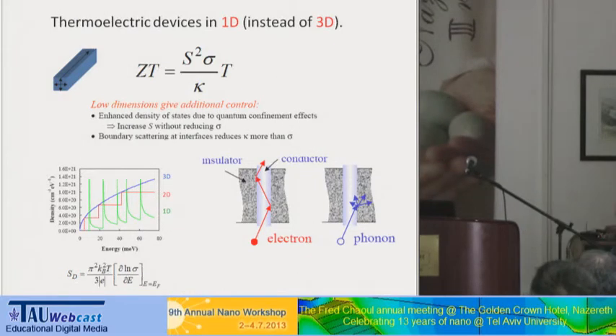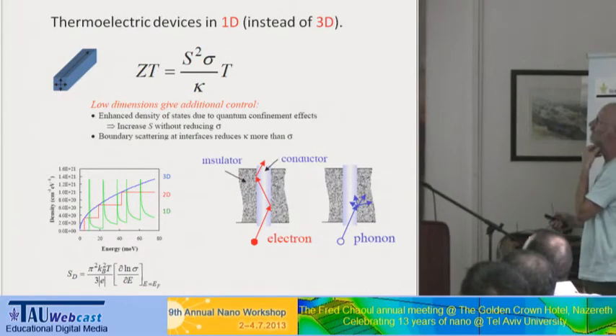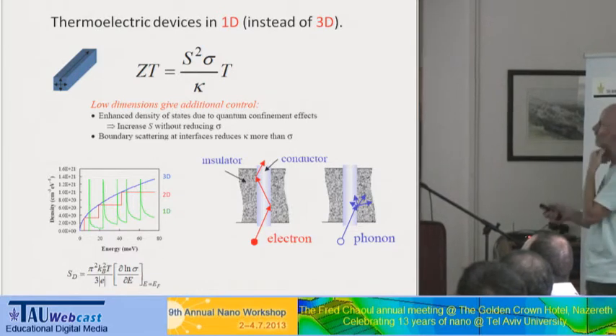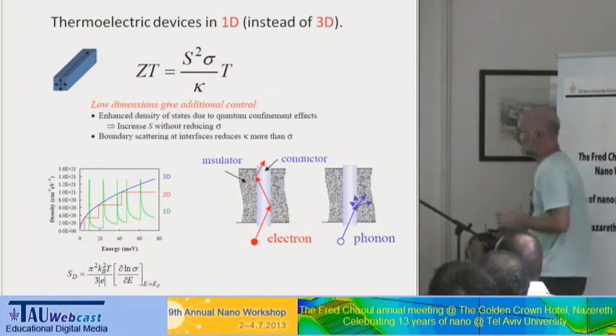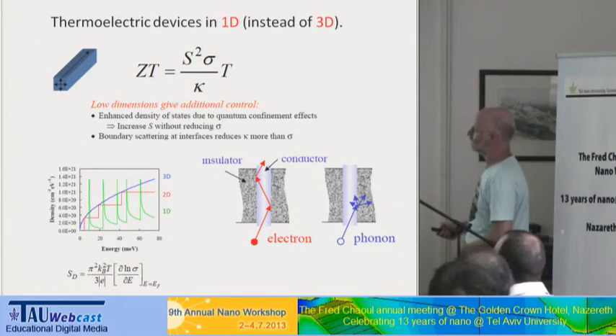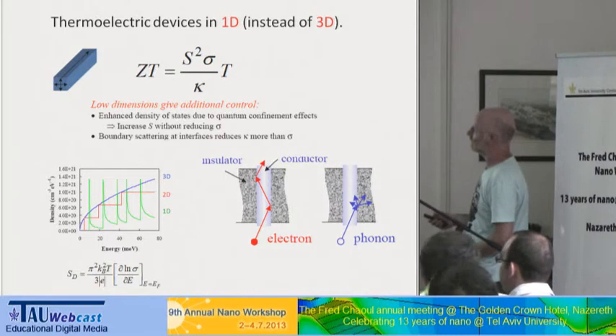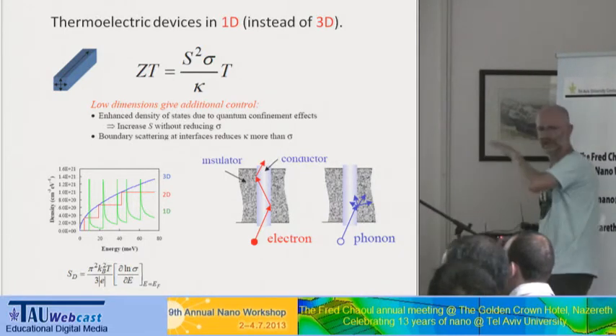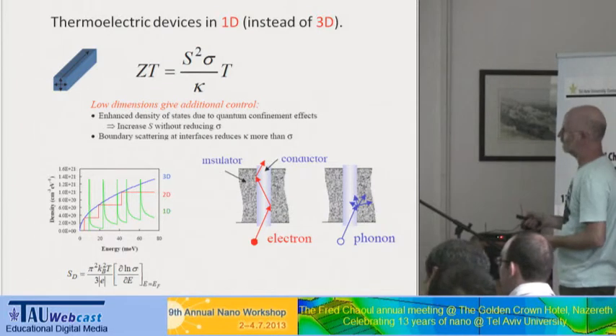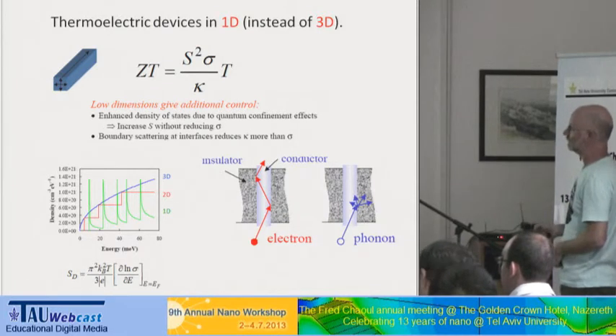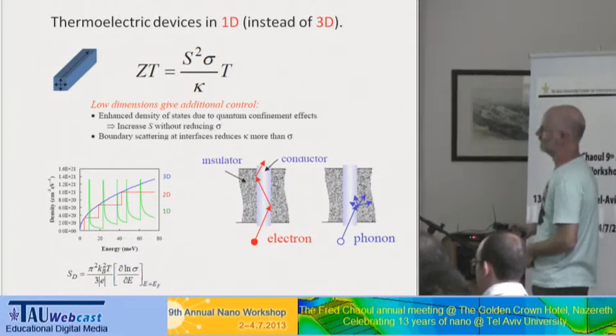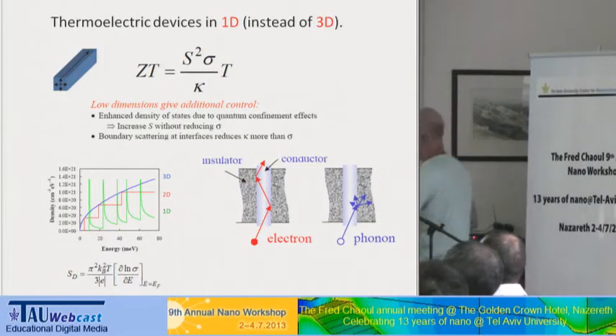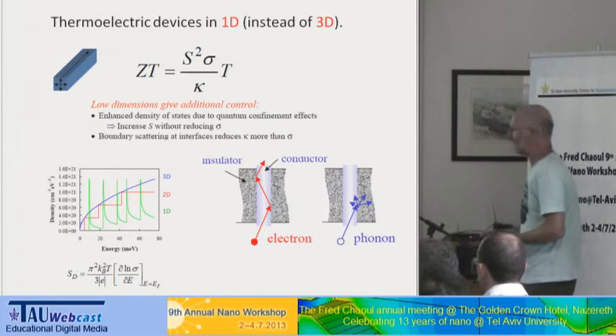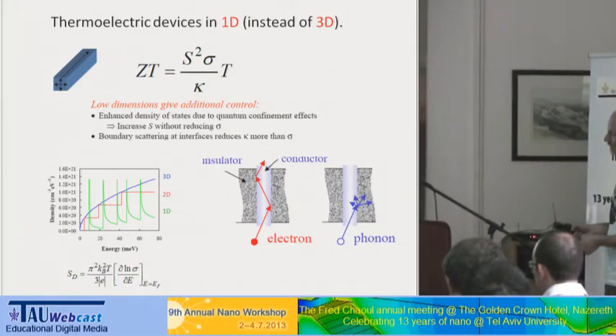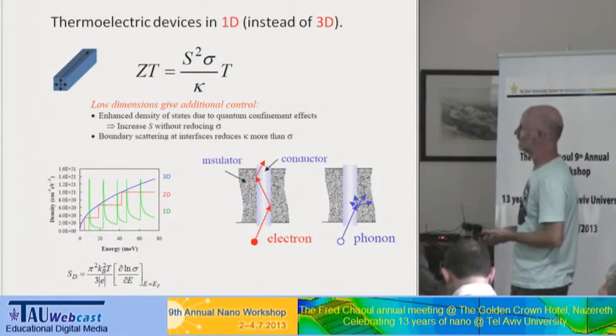Now, several years ago, someone said, you know what, let's work with one-dimensional materials in order to have really efficient thermoelectric devices. And the idea was the following. If you look at the density of states of a one-dimensional material, one-dimensional material means that in this direction and in that direction, the energy levels are quantized, and it's not quantized in only one direction. So if you look at the density of states, it's spiky. This is the green curve that you see here. So here the density of states, as a function of energy, is spiky. And I've shown you before, mathematically, if you have spiky density of states, you should have high Seebeck coefficient. So this is one reason why we need to work with one-dimensional conductors.